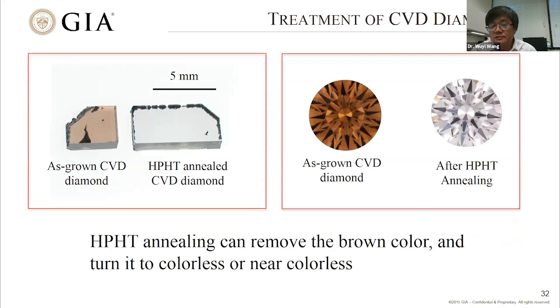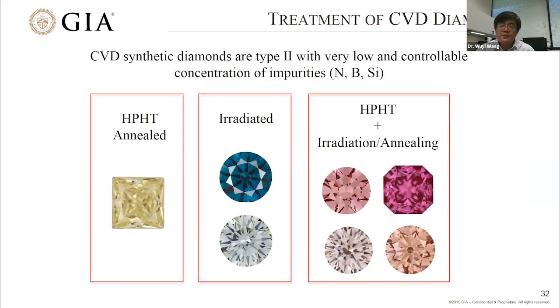The treatment not only applies to natural diamonds, it can also be applied to synthetic, and I just try to mix the terms synthetic or lab-grown diamonds. For lab-grown diamonds, like CVD lab-grown diamond, many of them show brown color, as we mentioned at the beginning. After HPHT treatment, the brown color could be removed. So it is very often we see in the trade that a CVD diamond was HPHT annealed to remove the brown color. Here's basically some summary of the major CVD color of a diamond with some additional post-growth treatment.